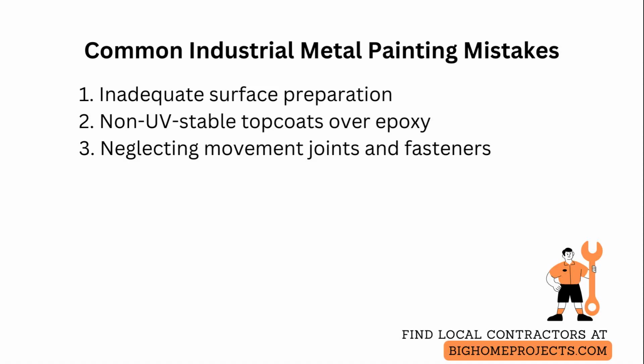The cure is to remove corrosion and contamination to the recommended cleanliness standard and verify with a surface profile gauge or reference standards. Another frequent problem is using non-UV stable topcoats over epoxy primers, causing chalking and discoloration. Avoid that by specifying an ultraviolet stable polyurethane or fluoropolymer topcoat and following the manufacturer recoat windows.